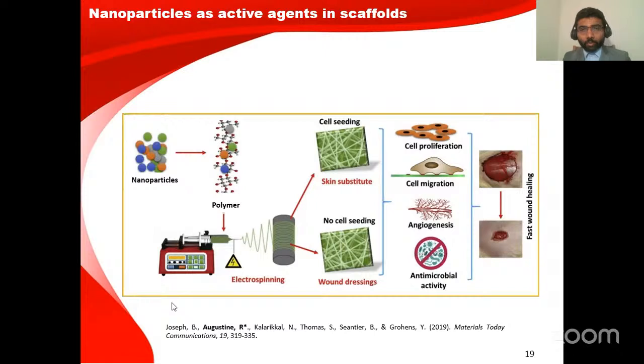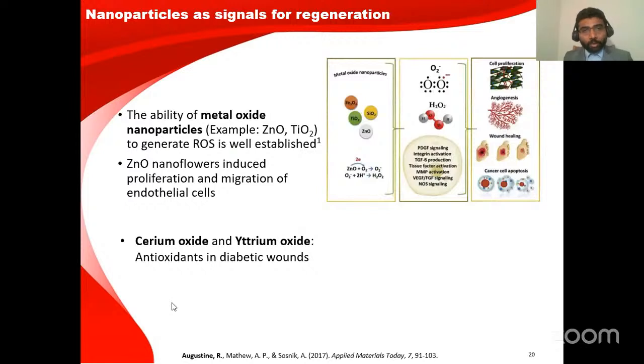When incorporated in the polymeric scaffold, these were able to support cell proliferation, cell migration, and angiogenesis. Angiogenesis means the blood vessel formation. They also provided antibacterial activity, especially the zinc oxide nanoparticles, ultimately resulting in higher wound healing activity. For example, metal oxide nanoparticles like zinc oxide or titanium dioxide are able to generate reactive oxygen species. Such reactive oxygen species are redox active materials in the biological system. At optimal concentration, they can provide better cell proliferation and angiogenic response. However, if the concentration is higher, excess reactive oxygen species can cause deleterious effects as well. So also we use zinc oxide nanoflowers for higher endothelial cell migration and so on.